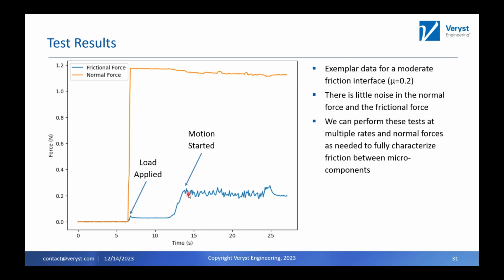And you can look at these loads that we're measuring. This friction force is 0.2 newtons, a friction coefficient of 0.2. In a project for a client that we did, we measured friction forces from 0.05 or 0.06 all the way up to like 0.25. It's a great tool to measure these very tiny friction forces.